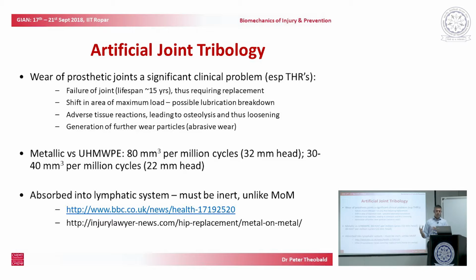Tribologically, we would go for a large head because that increases the velocity, but at risk of increasing wear because it slides further. But wear studies are only indicative to a point because of the limitations. But ultimately, the aim is to avoid the generation of wear particles at all, because as soon as you get wear particles generating, then it effectively acts as grit within your lubricant, and so it accelerates further injury. And there are a couple of links to stories about metal-on-metal implants. And that is that engineers understand and recognize the importance of having biocompatible materials.